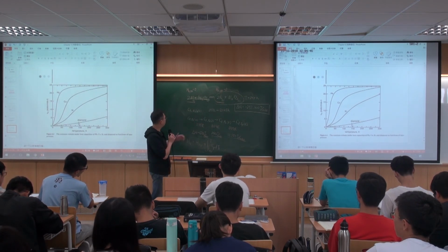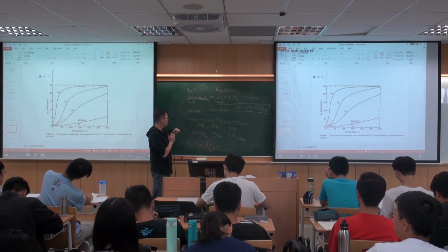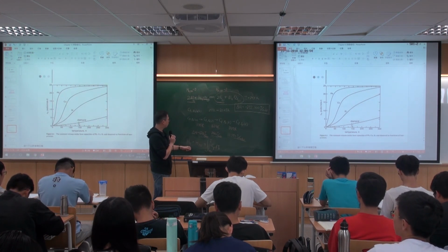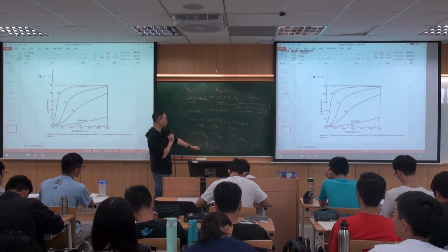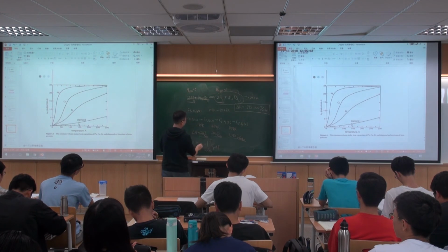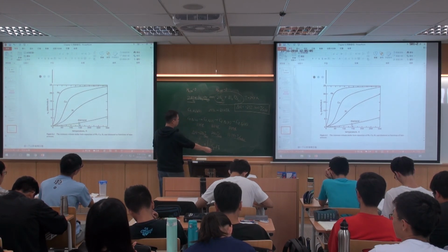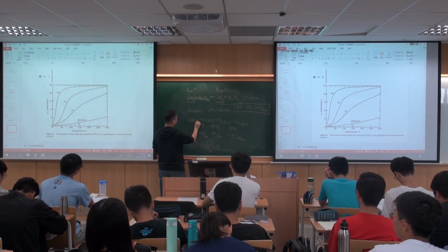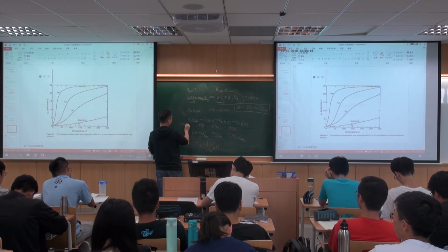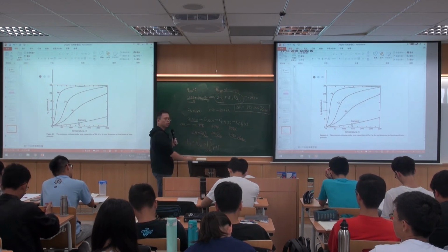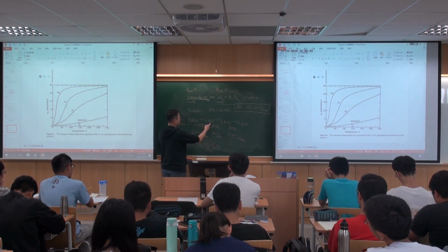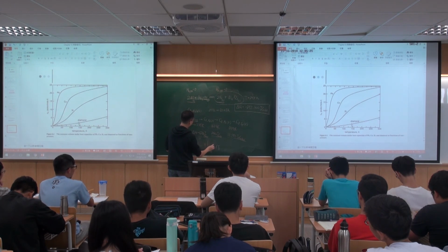So for each material, like for iron and aluminum oxide, you're going to go through the calculations based on this. For instance, for iron, we know that H298 should be 0, because iron at 298 should be 0. So you start from 0, and then for each phase, you have a certain CP. So this is only allowed from 298 Kelvin to 1,187 Kelvin. If you go beyond that point, then you have to do this.